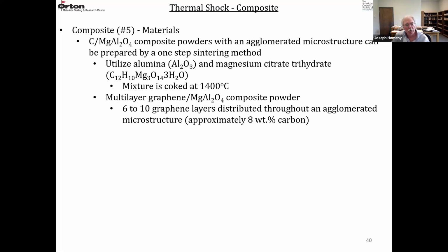And then the final product, what you end up with is a multi-layer graphene. So graphene is one layer of carbon atoms. They're in hexagonal rings, just like in graphite, but it's one atomic layer. But in this composite powder, it is multi-layer graphene, usually 6 to 10 graphene layers that are dispersed in this agglomerated mixture of graphene and spinel. And the carbon content from the graphene is about 8%. So you have this powder with nanoparticles of graphene dispersed in spinel with about 8% carbon.